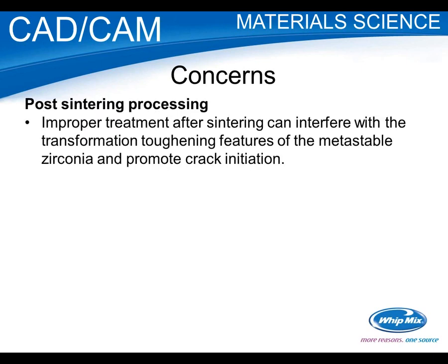Now, the concerns. Post-sintering process. Early on, there were a number of issues because labs and doctors tried to process it like they would a porcelain. So they grab their grinder and their burr and start cutting away to make the restoration fit. And that's a no-no for zirconia.